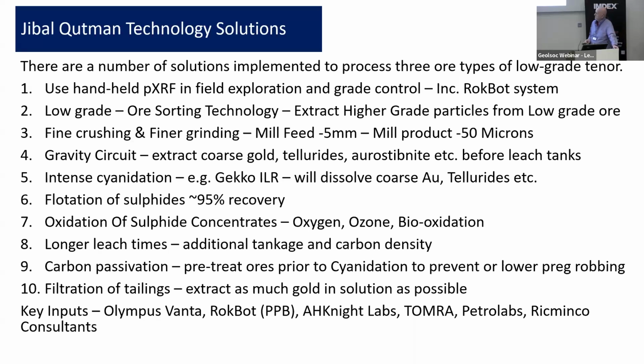Fine crushing. There's a lot of interesting work that can be done if you fine crush the ore before it goes into a ball mill. Standard practice, especially people that use SAG mills, they're using rather large lumps of rock, and it takes a long time and a lot of energy to grind this material down. So we're looking at using 5 millimetres into a ball mill rather than 25, which is standard practice. That allows the ball mill to grind it much finer, which allows you to get to some of these particles, which are generally very fine, inside the rock matrix to allow access to cyanidation. And that's very important if you know how much of the gold is exposed to leaching early on in the testing.